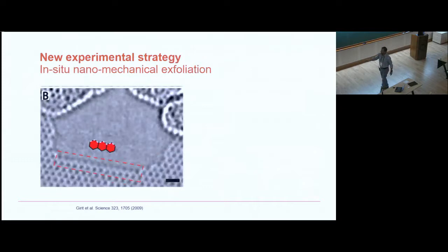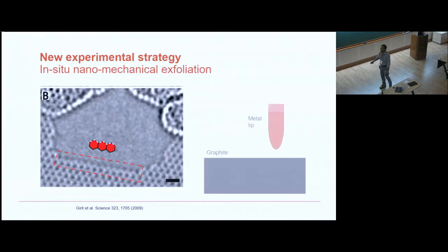We essentially did this experiment by taking a different route altogether. We decided that the graphene edges can be maintained if you simply rip it apart. Imagine a hexagonal sheet of paper. What you do is simply tear it. And if you do so, it turns out nature gives you the possibility of having pristine edges. This was shown by the Berkeley group quite a while back, actually. And this is ruptured graphene, and it shows beautiful zigzag edges for very long distances.